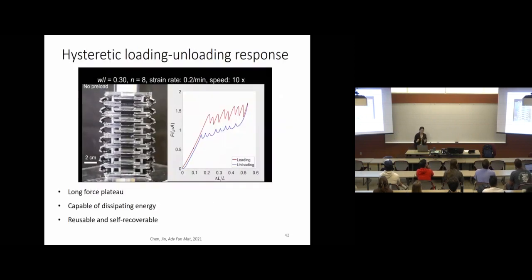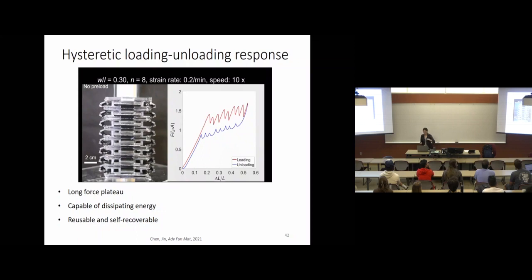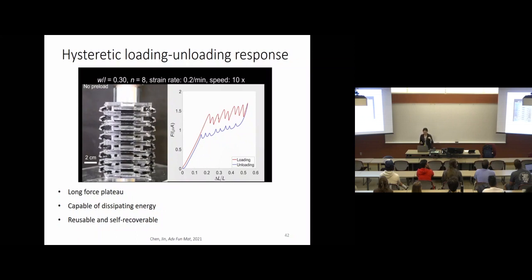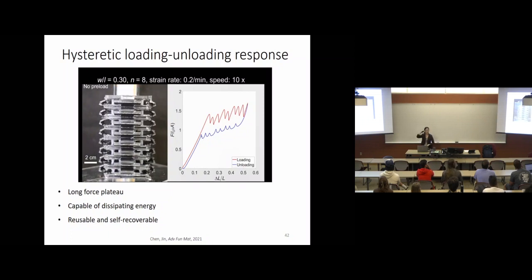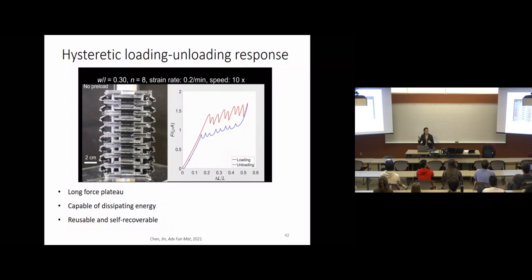Here I'm showing you the behavior of this metamaterial during loading and unloading. During loading, you observe 8 peaks corresponding to the buckling of these 8 layers. You also see a long force plateau, which means force mitigation in this material. Then during unloading, again, you see 8 peaks corresponding to unloading of these 8 layers. The loading and unloading curves do not overlap, but there's a hysteresis indicating energy dissipation through this process. And once you unload the material, it immediately recovers its original shape, which means it's reusable and self-recoverable.